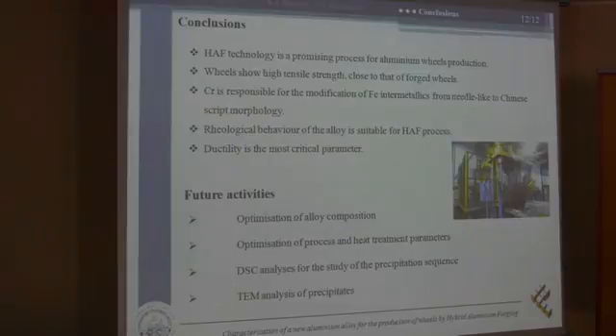So in conclusion, we can say that the HAF technology is a promising process that will show, for sure, a high tensile strength, very close to that of forged wheels. That chromium is mainly responsible for the modification of intermetallic phases from a needle-like morphology, which is more detrimental, to a Chinese script morphology, which is instead less harmful. Then also the rheological behavior is positive, but still ductility is the critical parameter.